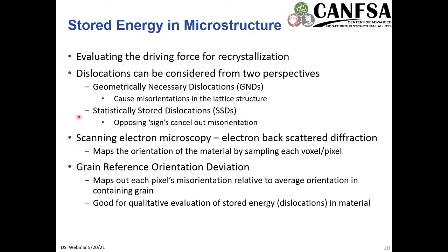We wanted a spatially resolved technique, so we used EBSD mapping, and so we were looking at GNDs. We are, in some sense, ignoring SSDs, but the assumption being made here is that you're not going to have too much of a discrepancy in distribution between these two. Utilizing scanning electron microscopy and electron backscatter diffraction, this maps the orientation of the material by sampling each voxel or pixel, and then it does some analysis to determine which grain that pixel belongs to, and plots those grains on a map. With this information, using grain reference orientation deviation, a mouthful, but a GROD technique as I'll call it, this maps out each pixel's misorientation relative to the average orientation of the containing grain that it was just calculated to exist within.